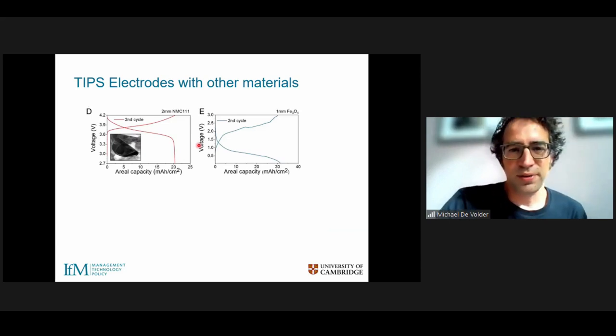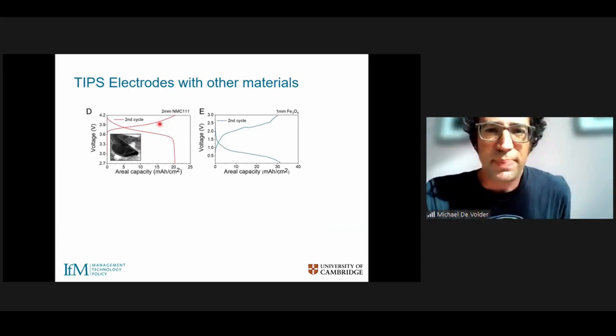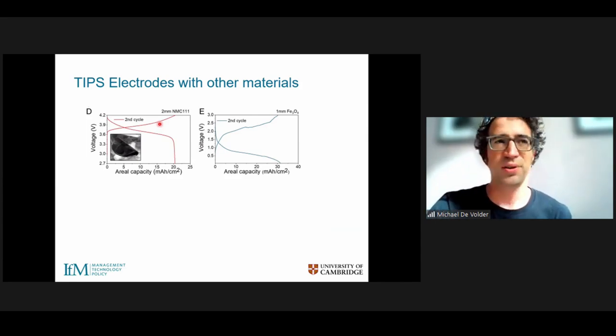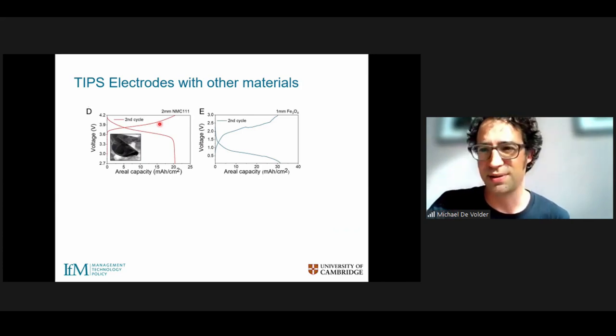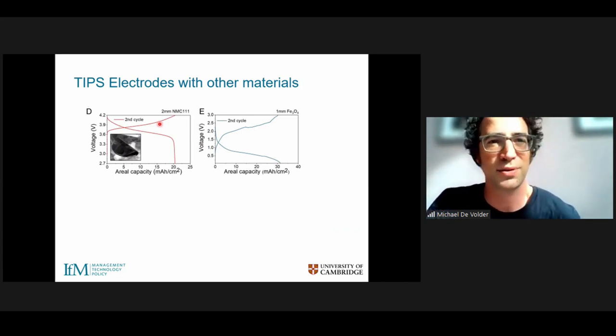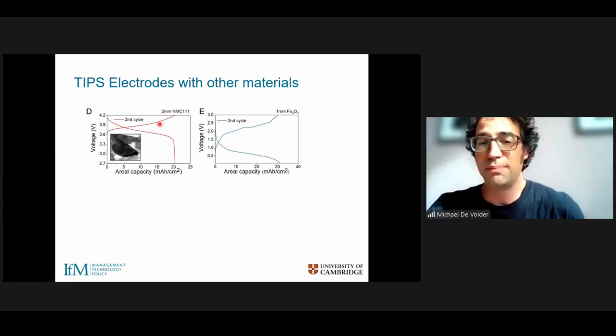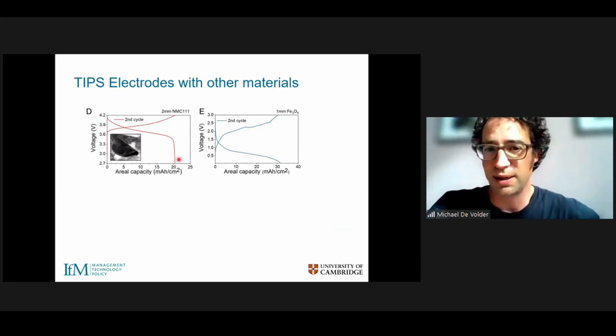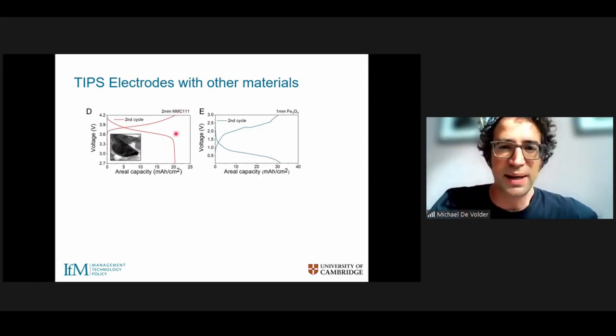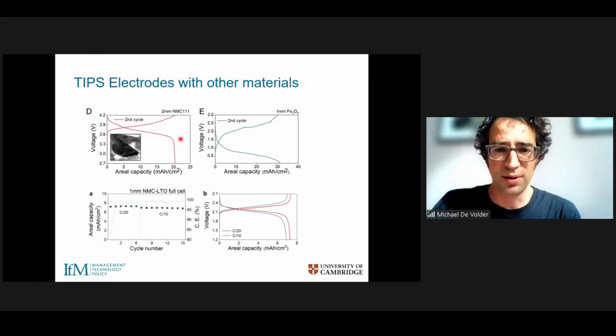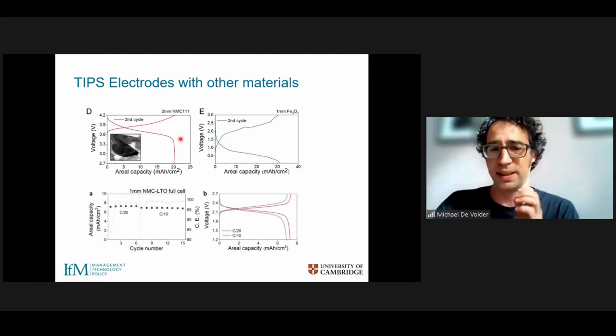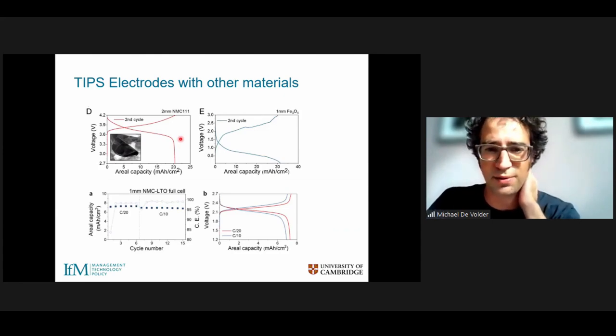So what we've done next is some experiments to show that the properties we've measured are not limited to just the two materials I've talked about so far. So far I've talked about lithium iron phosphate and lithium titanate being possible materials for using with this process. And here we show that other popular battery materials such as NMC cathodes, a mixture of nickel, manganese, and cobalt with lithium, operate well with this process also. And so we can combine different types of material to form what people are calling full battery cells typically.